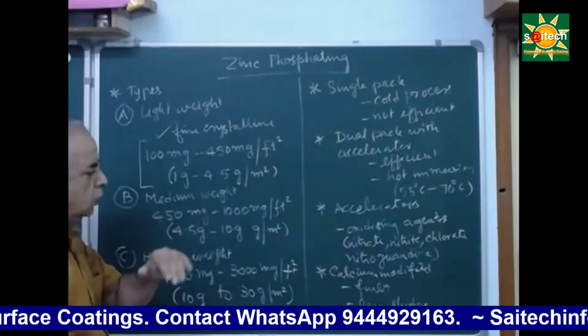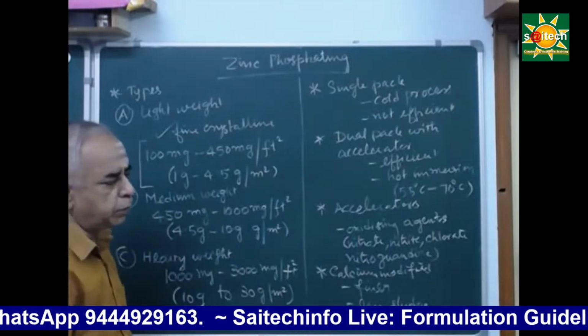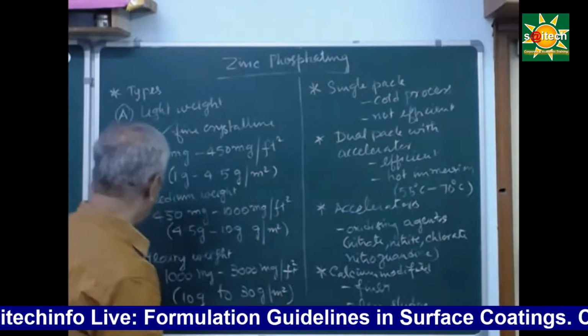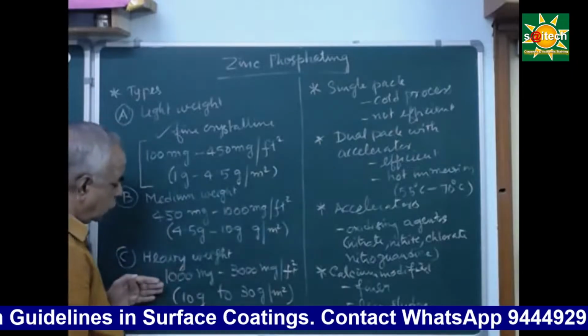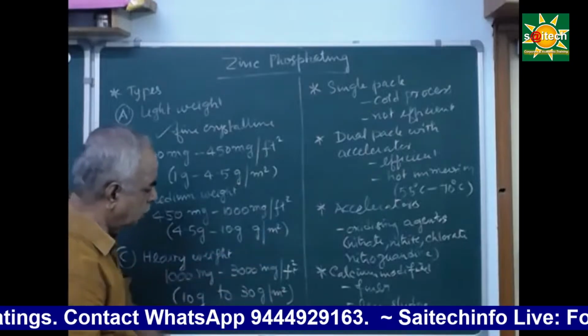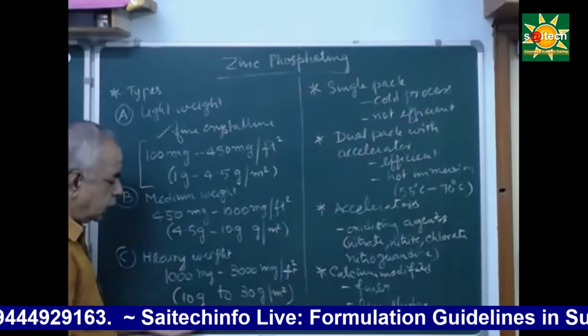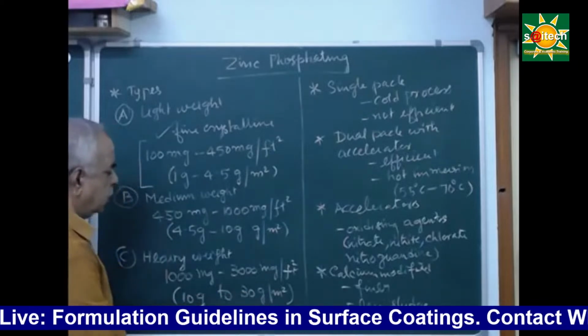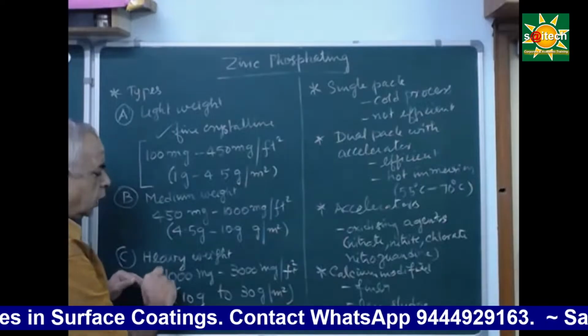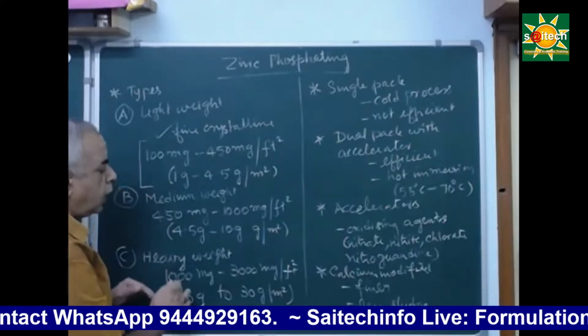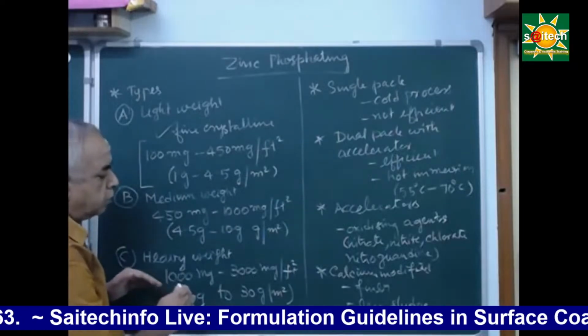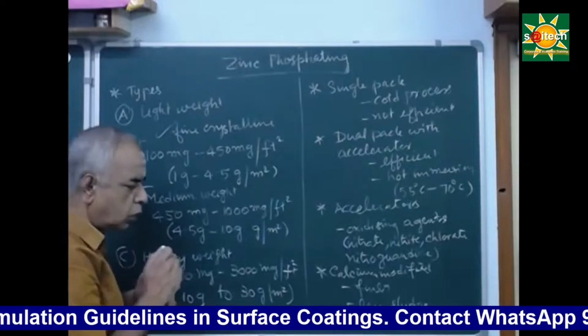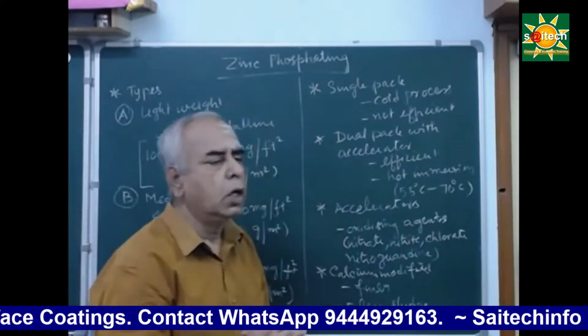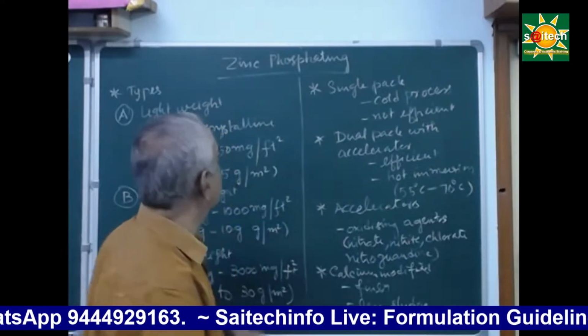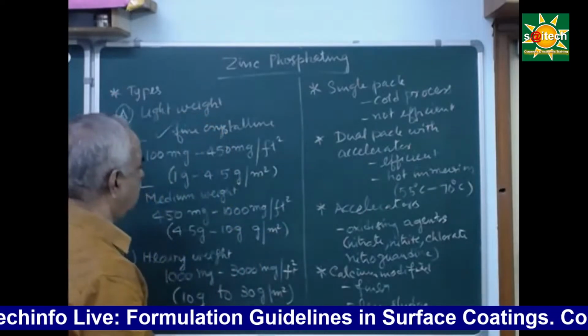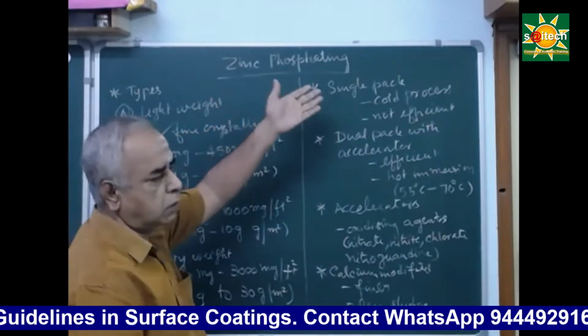phosphating, they will give the top coat, the finish coat, with liquid paint or powder coat. And the third variety is heavy weight. So here it is 1000 milligram to 3000 milligram per square feet, that is 10 gram to 30 gram per square meter. Here it will be slightly porous, and it may not have an aesthetic appearance, and it will have a matte finish also. So if you want to have a super glossy finish with a single coat of finish or double coat of finish, then I would suggest you go for lightweight, where you cannot get the highest corrosion resistance.